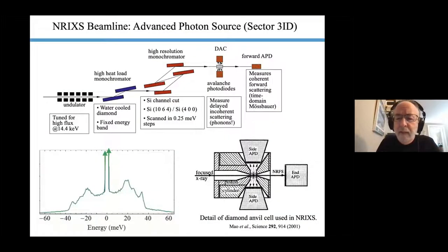Well, we worked at sector 3 and we got some nuclear resonant inelastic X-ray scattering with a technique which goes through the nuclear excitations from iron 57 for the ground to excited states. And these are very, very sharp in energy. They're negligible on the scale of millielectron volts. They're downs of tens, hundreds of nanoelectron volts, in fact. So the shape of this main resonance is set by the quality of this high resolution monochromator here.